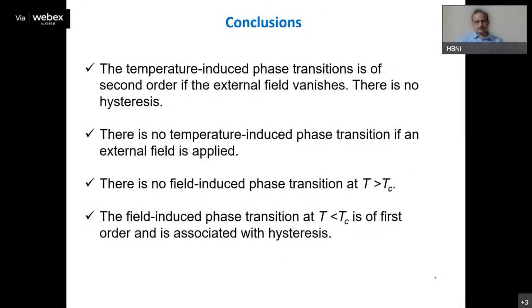Now, before considering the other case of first order phase transitions, let us conclude whatever inference we get from this analysis. One thing is that the temperature induced phase transition is of second order if the external field vanishes. So there is no hysteresis. This is the case when there is no field.